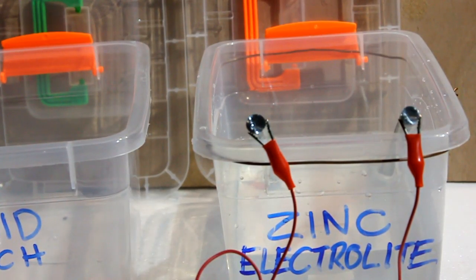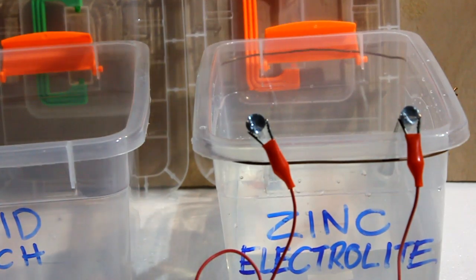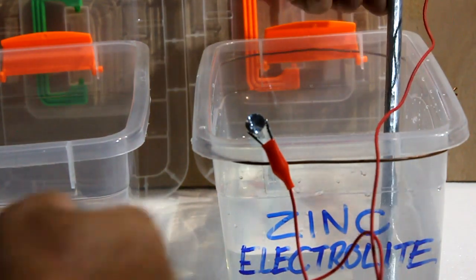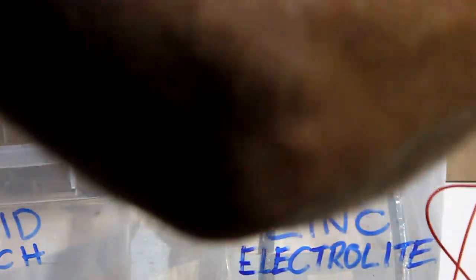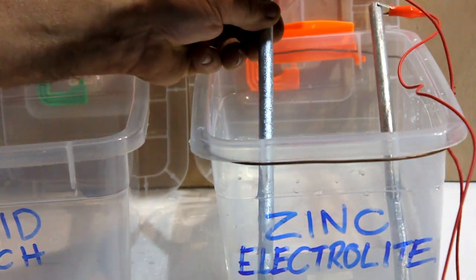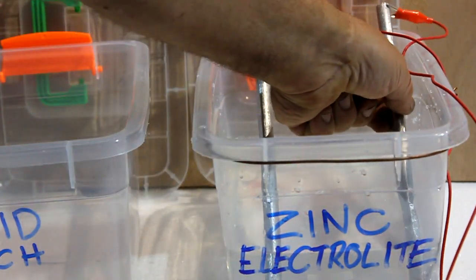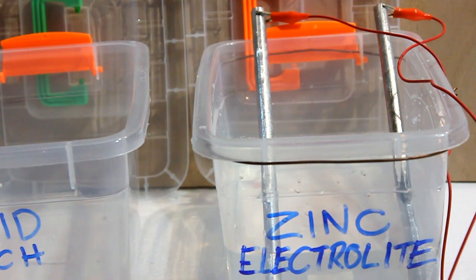I've now plugged in the two electrodes. They're sitting in the vinegar. They must be kept away from each other. You'll see that we've got just one terminal gassing, that's the negative terminal. We're going to leave that for 20 minutes to half an hour and then the electrolyte will be ready to use.